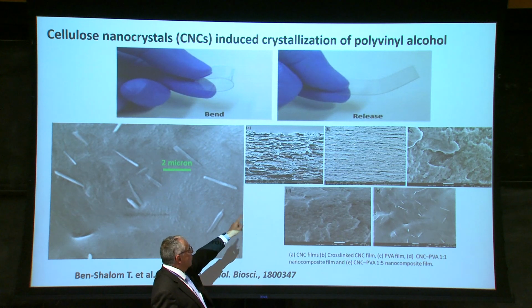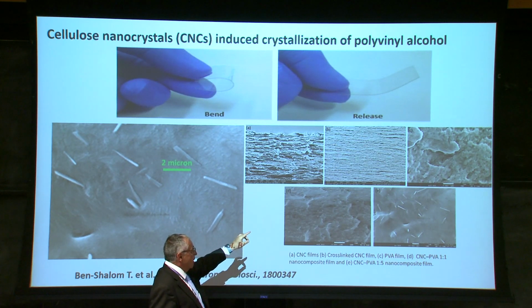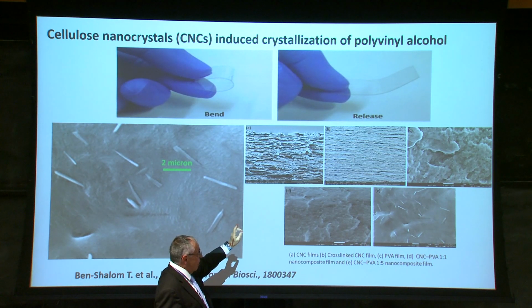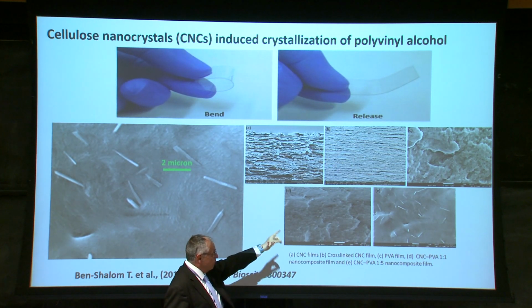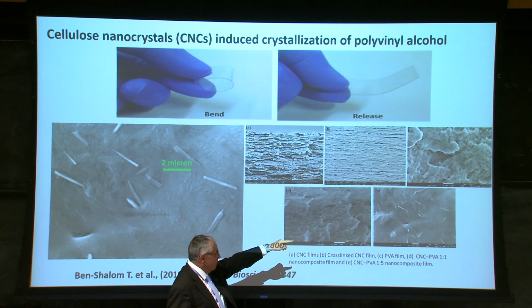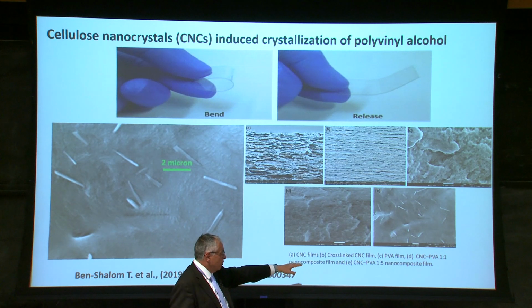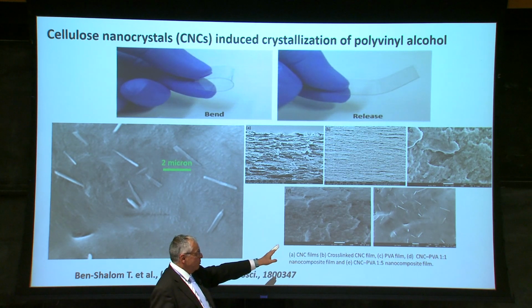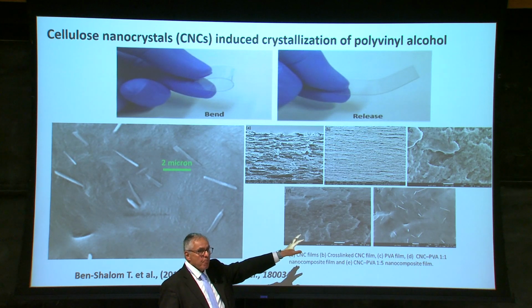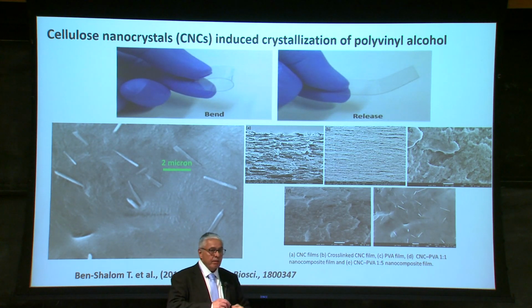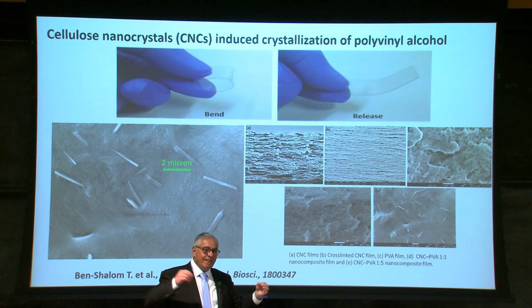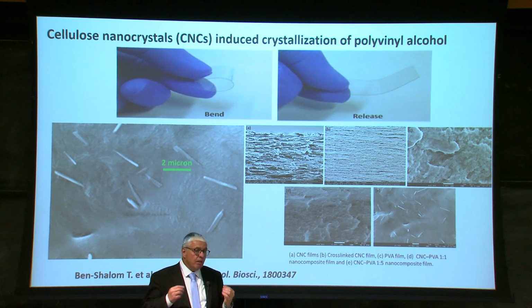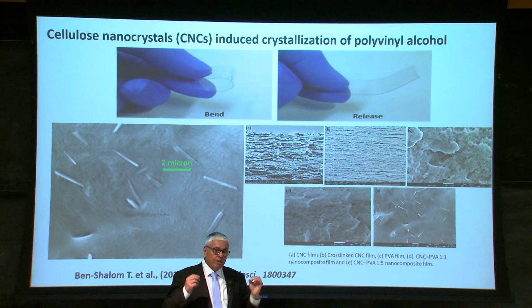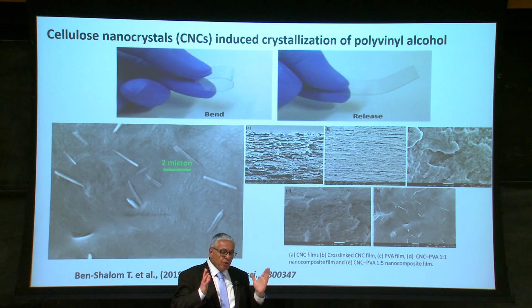And here on the bottom, it's polyvinyl alcohol CNC at a ratio of 1:5, or 5:1, sorry. And here it's 1:5. So 1/5 of the material is CNC and 5 is PVOH. And you can see there is a clear difference. What we see here on the right panel is that we're actually forming very long needles. It turns out that these needles are actually made of PVA, highly crystalline PVA. So the cellulose nanocrystals serve as a template to actually grow very long and very strong crystalline PVA.